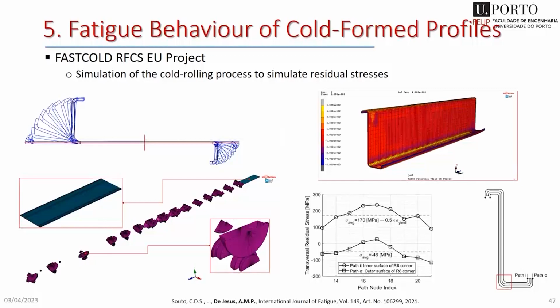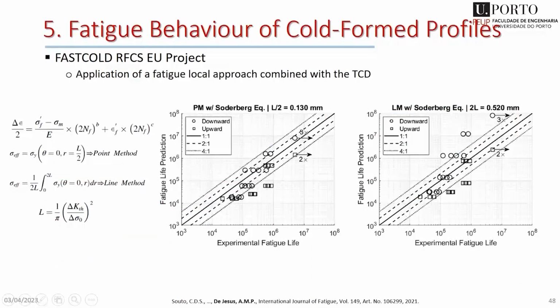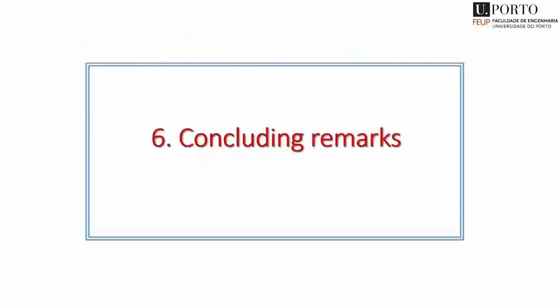But anyway, we went to modeling. I'm just finishing, just one more slide. In this case, we have to simulate the profile production using numerical modeling, just to get the residual stresses in the corners. And with that, we applied local approaches, like the critical distances theory that we heard about before for fracture. Now I'm talking of that for fatigue. We applied that, and we succeeded in predicting the fatigue life of the profiles.